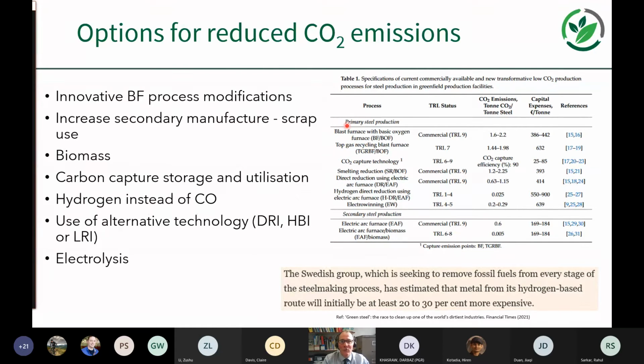So, options for reduced CO2 emissions. In the table, we can see the blast furnace with the basic oxygen furnace route for producing steel, between 1.6 and 2.2 tons of CO2 per ton of steel. Then top gas recycling brings that down, and carbon capture brings that down further. Then you've got direct reduced iron with the electric arc furnace, which starts to bring it down further. And when we start to consider hydrogen, we're bringing those specific CO2 emissions right down. So it's possible even with primary steel production to bring those emissions down.